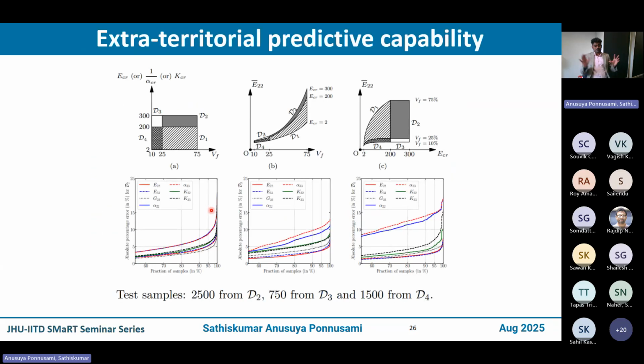Okay. So now, obviously, we have a design space for the data set generation. But then what if you extrapolate or you force the model to predict out of the bounds? And that is why we have three different data sets that you see, D2, D3, and D4, which are in the extrapolated domains, widely extrapolated domains, which are not physically needed for practical purposes because engineering design does not go into that space. But nonetheless, what we really want is to check how the model can extrapolate reasonably well. And of course, the disclaimer is we are not extrapolating significantly out of the domain, but we still go reasonably far out of the bounds of the design for the data.